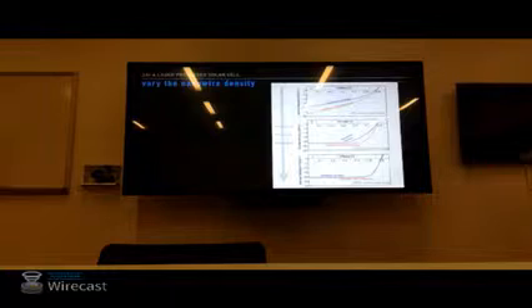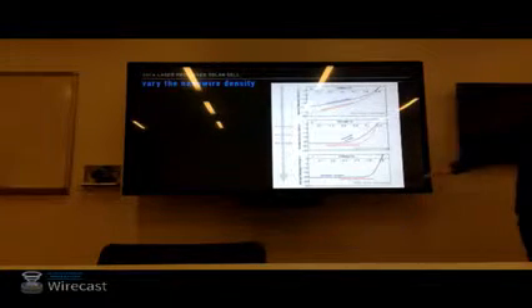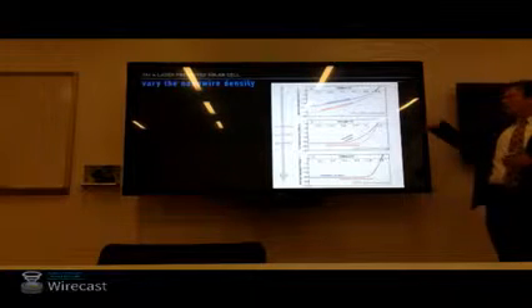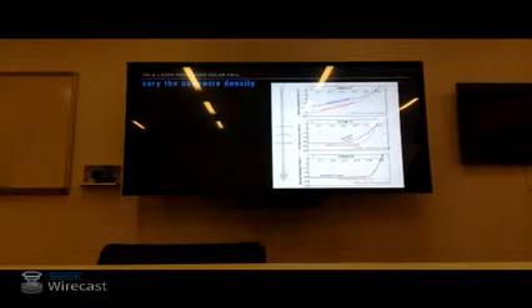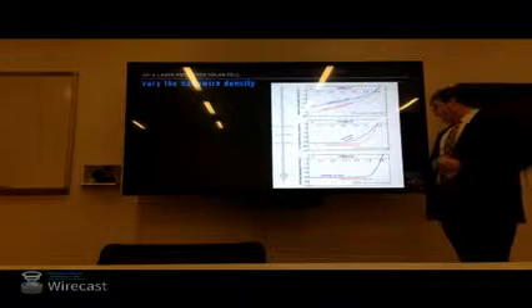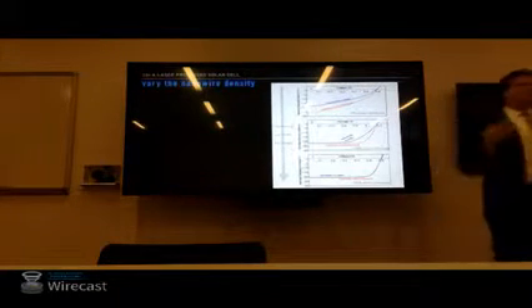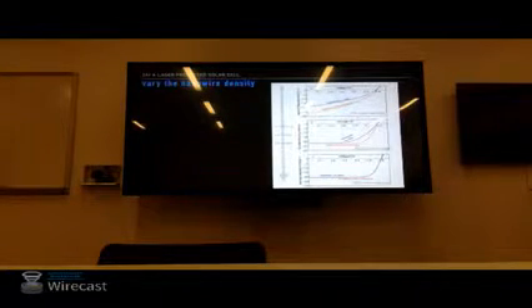So let's see what happens when we apply to a more optimized device. So if we do 3 levels of nanowire, kind of a high, medium, low, 6% area coverage, 16 and 25, we see different behavior going on. The 6%, we take a very bad device, we make it better, but it's still not great. In the very high area coverage, we have a really good device to begin with. Laser doesn't do much. Actually, we're happy about that. We don't want the laser hurting the device. So it's nice that we have a good device that stays good.